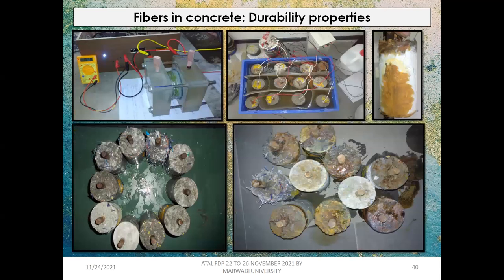Again, we worked on chemical resistance. You can see here the rapid chloride penetration test, the RCPT, that we employed. We went for accelerated corrosion, and then we obtained comparative results using the fibers in concrete. Here you can see somewhere the fibers are still visible and the surfaces have been damaged, and we compared them with the non-treated, or control, mixes. Finally, we could say that definitely it helps to reduce the chemical impacts and effects on the surfaces.